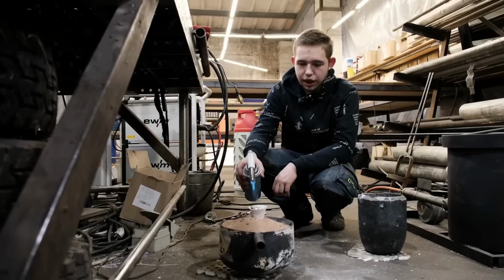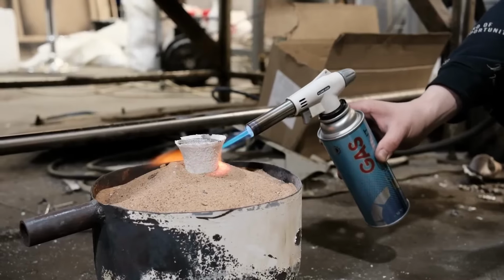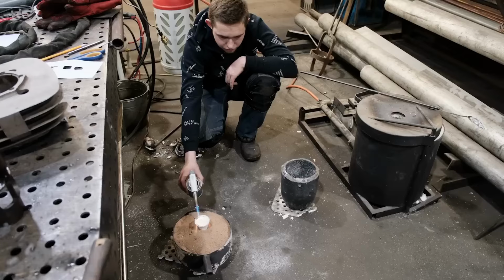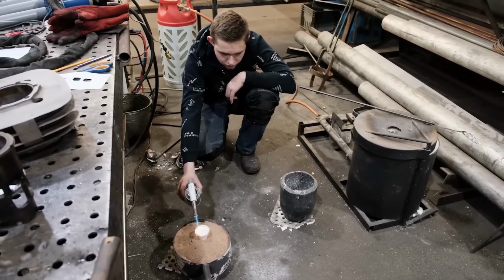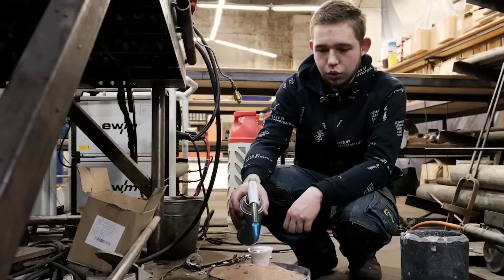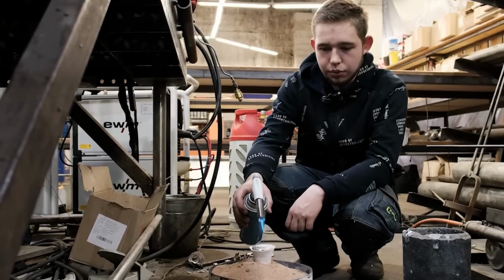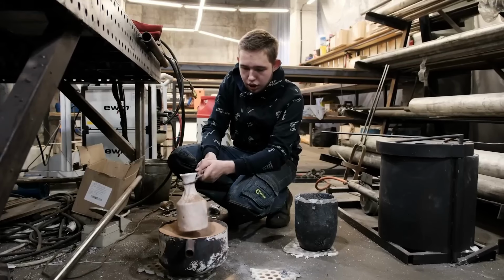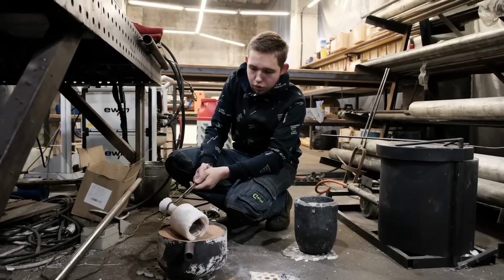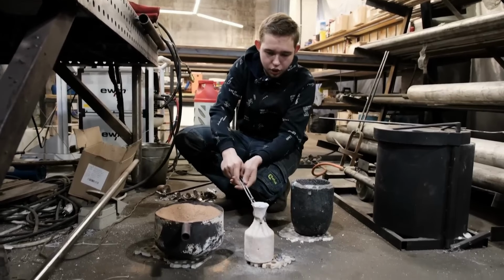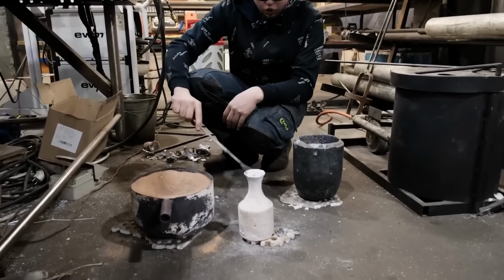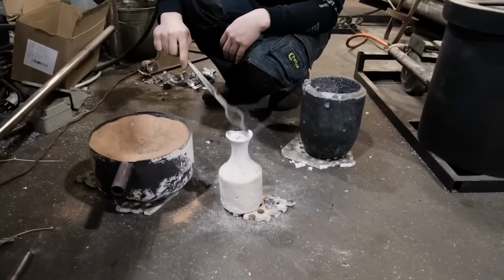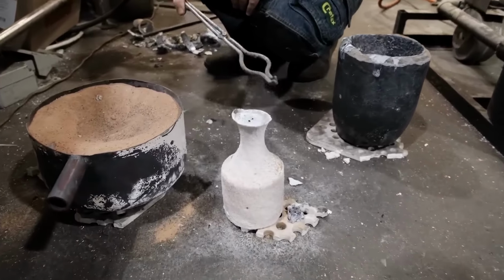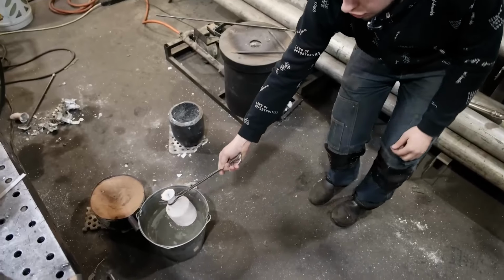We're gently and slightly heating the sprue from above, so that crystallization doesn't start at the top, but happens gradually. After a while, we'll see what we've got. Alright, let's gently take our mold out of the sand, the one we've poured. Now, we'll let it sit for a bit longer and allow it to cool down. And then we'll see what we've got. Now we're cooling down our mold.